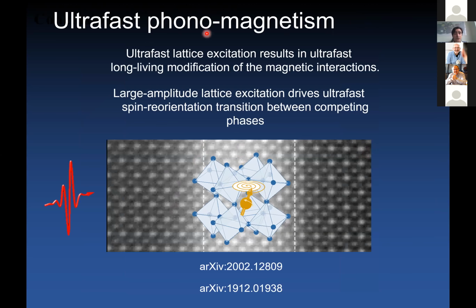Okay, so that's my final summary. By exciting on the ultrafast timescales the lattice at surfaces, at interfaces of these transition metal oxides, you can induce long-lived modifications of their magnetic interactions and drive spin reorientation phase transitions between competing magnetic phases.